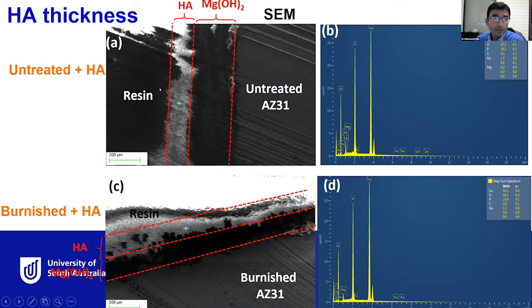We also looked into the cross-section of the coated surface by SEM and also EDS. This is the untreated plus HA coated cross-section. Generally, this is the substrate, and then we can see a bit of formation of magnesium hydroxide. This is very common when you deposit any kind of HA coating onto magnesium, because it initially forms a very thin magnesium hydroxide barrier layer, and then on top of that we have the HA coating. And we can see exactly the same thing in the burnished plus HA coating.